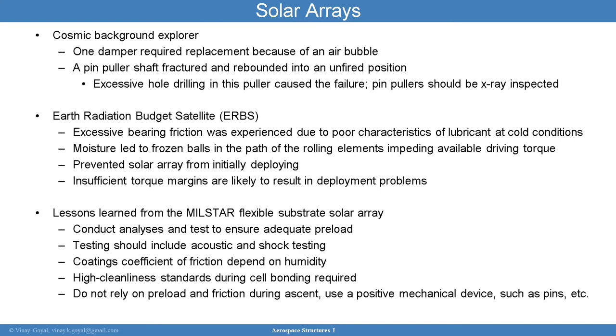The Earth Radiation Budget Satellite experienced excessive bearing friction and poor characteristics of lubricant at cold conditions. You see this theme a lot, where cold conditions with lubricant can be a problem. Moisture led to frozen balls in the path of the rolling elements, and that impeded movement of the drive torque. It prevented the solar array from initially deploying. So you have insufficient torque margin, and these are likely to result in deployment problems.